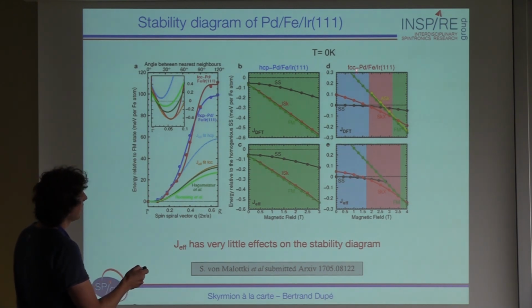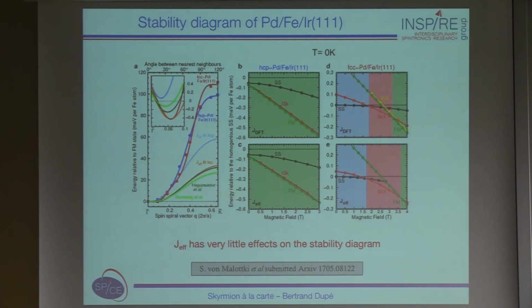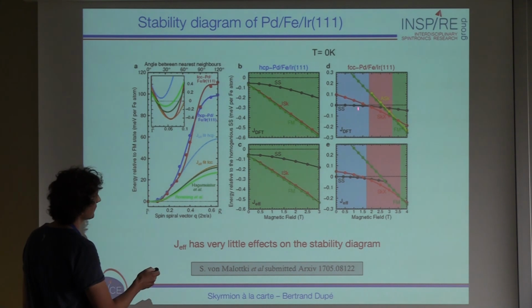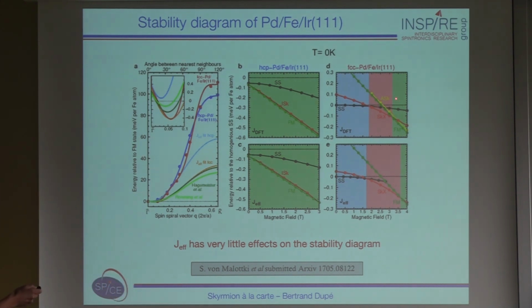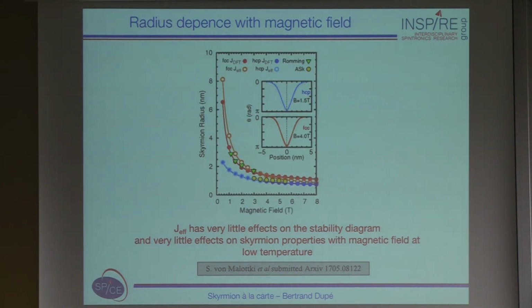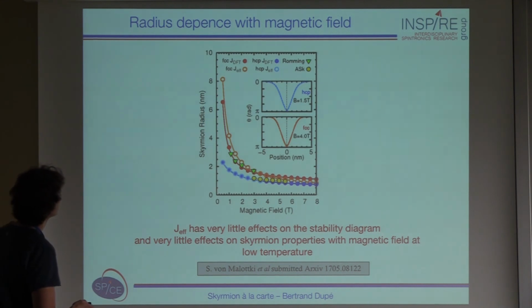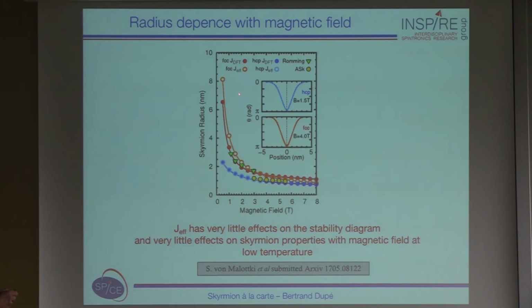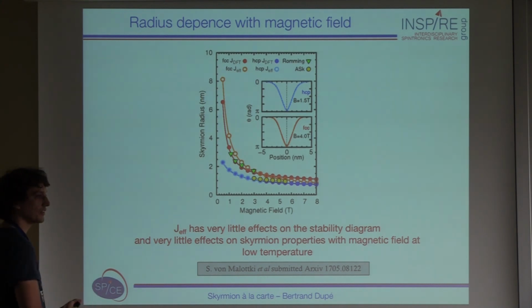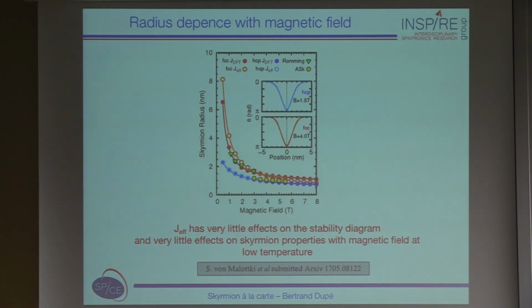In the case of the palladium FCC, it's actually also the same. You have actually not so much difference here, except one line, which is here a line showing the stability of the anti-skyrmion. And that's quite interesting, because if you have frustration of exchange interaction, the anti-skyrmion might be stabilized. If you have only J effective, the anti-skyrmion is not stabilized at all. So now if you look not only at the ground state, we apply a magnetic field, and we look at a quantity such as the skyrmion radius, which characterizes the skyrmion, you see that independent basically of all the parameters, you get something which is very similar. So it seems that if you stay close to the ground state, the frustration of exchange interaction and the J effective is actually not making any difference.